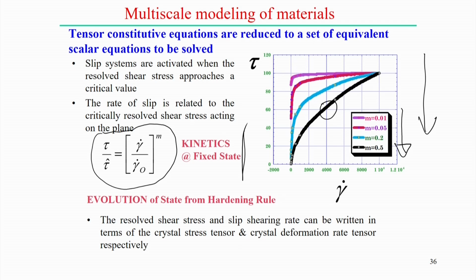With this behavior, it is possible to evolve the state from the hardening rule. The resolved shear stress and the slip shearing rate can be written in terms of the crystal stress tensor and the crystal deformation rate tensor respectively. I am not going into the mathematical derivation of all these phenomena, but ultimately we can form the constitutive relation in terms of the shear stress and the rate of shear strain, and accordingly we can evaluate the hardening rule even in the crystal plasticity model.